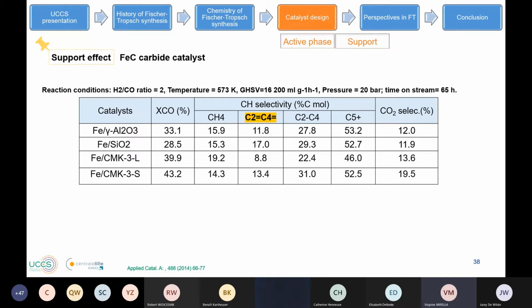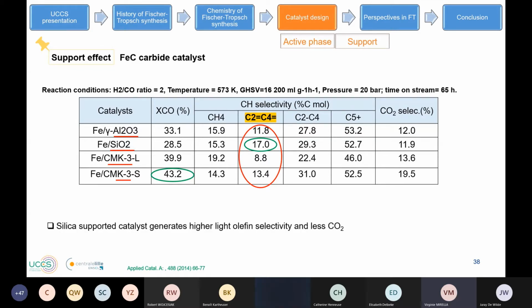We did the same with our iron carbide catalyst. We changed the supports, and we observed interesting conversion on carbon support. But when we look at the olefin selectivity, we observe a little higher selectivity when we use silica. So with silica, we had better interaction between our active phase and the silica support. So for iron, it seems that silica support is a little bit more interesting than mesoporous carbon materials.